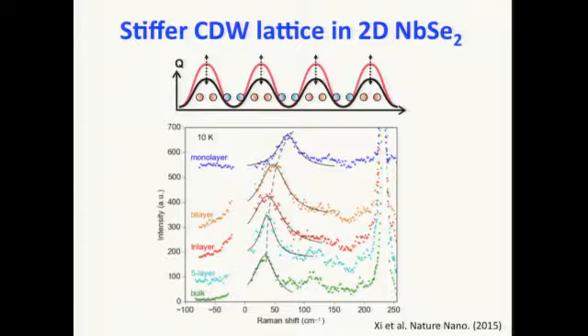A glimpse into the quality of the sample we make is when we cool down the material and then look at the Raman modes. And it turns out that actually the material is quite clean. We can still see the CDW order, or the charge density wave order, in this material. Actually, this shows the Raman spectrum corresponding to this CDW lattice vibrations. And you can see this mode here.